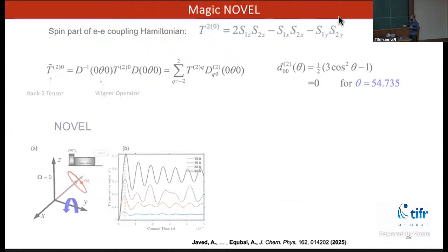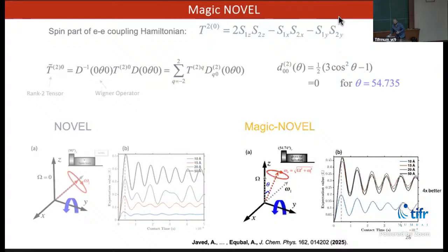Compared to that, in NOVEL the rotation is in the transverse plane. So one way to overcome this electron-electron coupling limitation is to do an effective spin lock at the magic angle. If we do the effective spin lock at the magic angle, we can see that the technique, magic NOVEL, is efficient even for shorter distances between two electrons as compared to simple NOVEL. In the NOVEL technique, the moment you have electron-electron coupling, the efficiency goes down. But here the technique remains efficient up to 15 angstrom distance between two electrons, 1.5 nanometer.